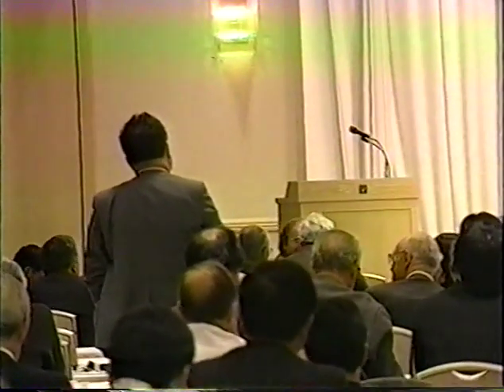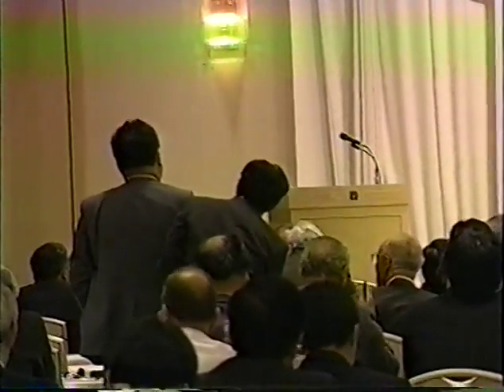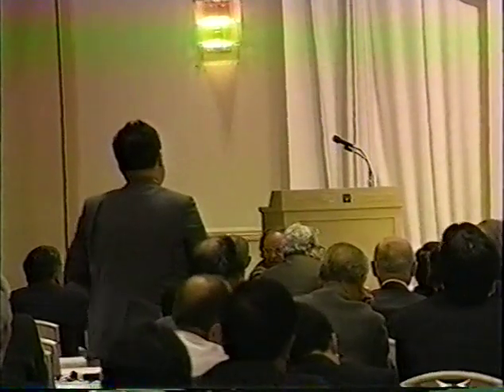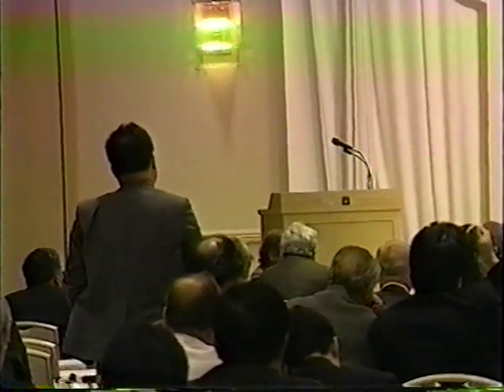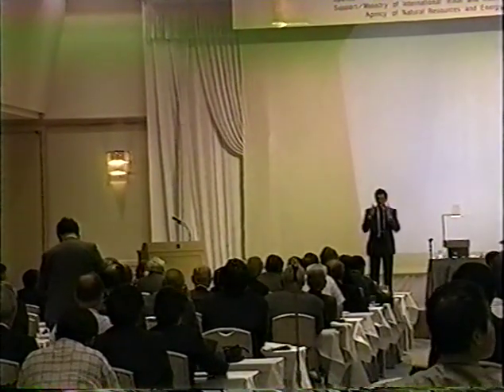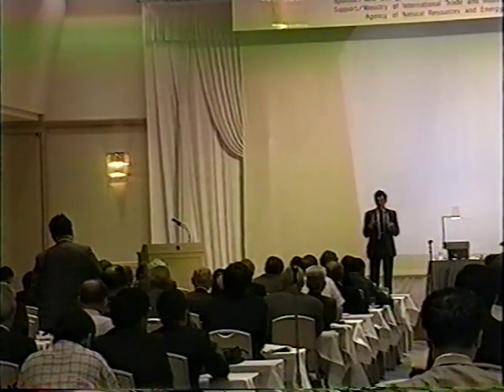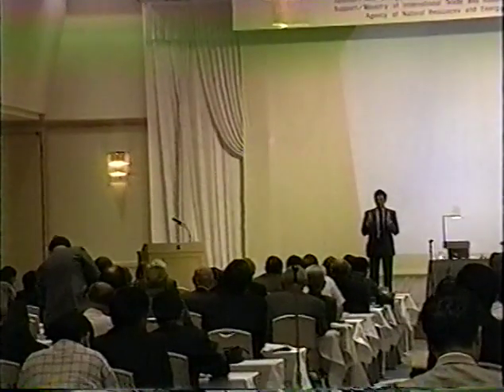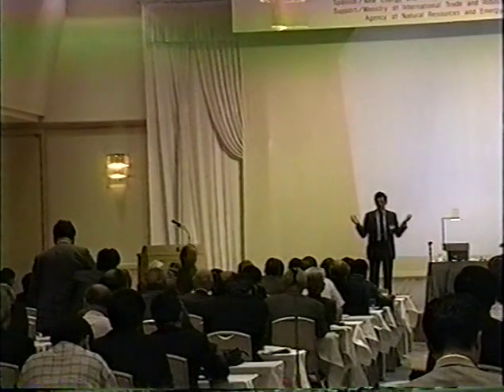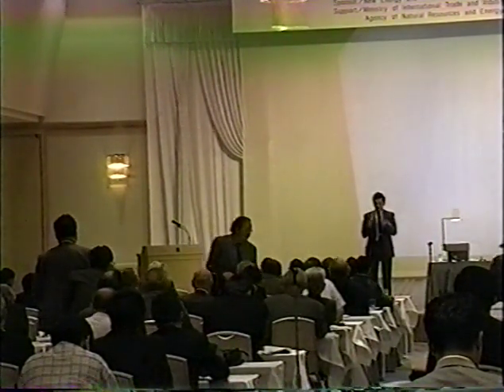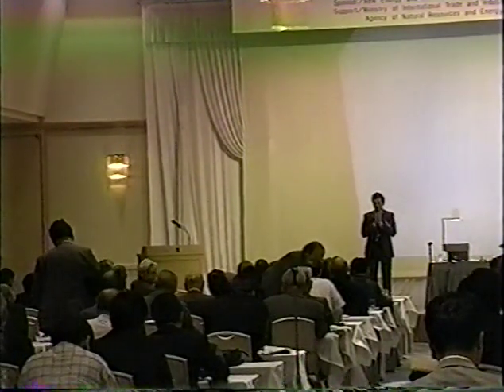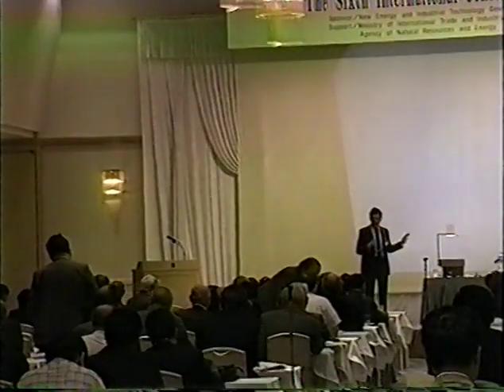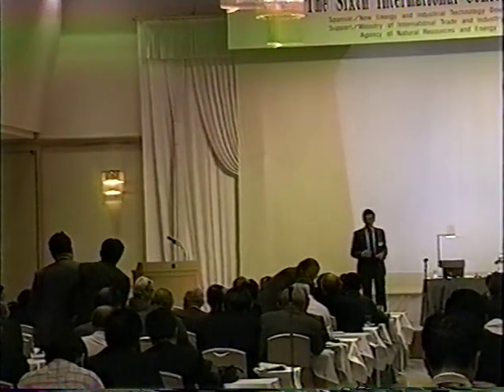Could you show the current waveform in source and load and endpoint? Sorry, could you please show the current waveform? No, in this experiment we use just DC current. What I showed before was the resistance changing over time of this element. We studied from 1 milliampere to 1 ampere, but no special wave. With pulse condition, we have a pulse with rise time of the order of 1 nanosecond to 500 nanoseconds, but now I didn't show it. So you are not pulsing?